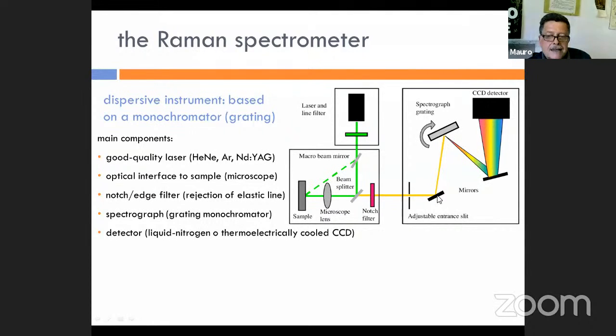The Raman signal is then analyzed by a spectrograph, but before analyzing, it must be filtered to remove the elastic excitation light. The filter used to remove the elastic line is called a notch filter. A notch filter has a sharp drop in transmittance just at the elastic line. So the notch filter transmits all the light except the elastic excitation line, that is, the laser frequency. We can also use edge filters, which have their advantages. An edge filter has not a drop, but just an edge of transmittance near the laser wavelength.